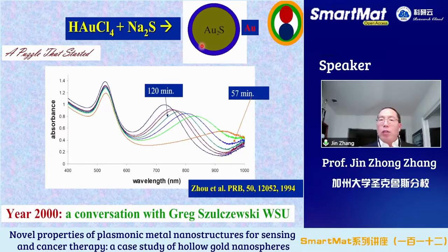Then I said, if it's not core shell, what do you see then? He said, I don't know. Well, we know enough about these structures then. He knows, and I also know, that this spectrum has two peaks, a major peak at 520. That is the typical characteristic absorption of gold nanoparticles. However, if you just have a gold nanoparticle solution, you should only see this 520 peak, nothing else.